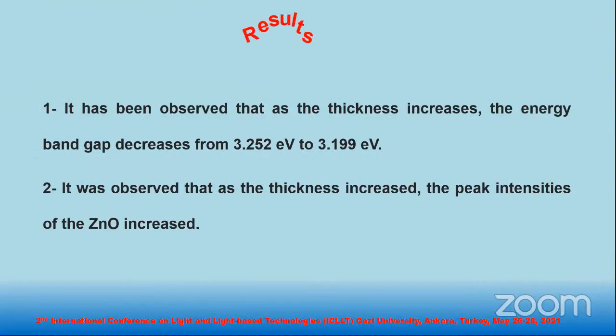Results. 1. It has been observed that as the thickness increases, the energy band gap decreases from 3.252 electron volts to 3.199 electron volts. 2. It was observed that as the thickness increased, the peak intensities of the zinc oxide increased.